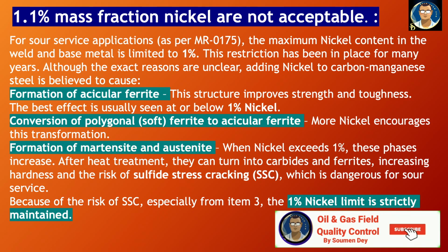So if you check these three reasons, the third one, what I mentioned, is more serious. When nickel increases, after the heat treatment they can turn into carbide and ferrite, which increases hardness and increases the risk of sulfide stress cracking, SSC. Because of the risk of SSC, the 1% nickel limit is strictly maintained.